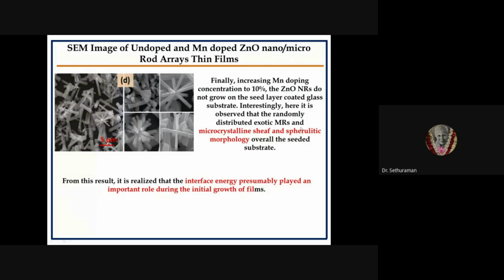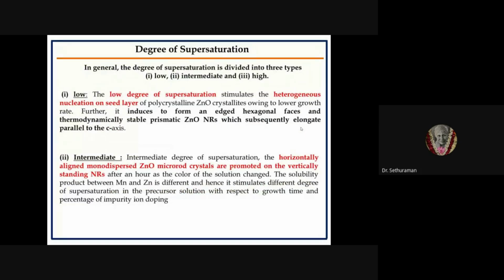Here, zinc oxide nanorods are not growing on this seeded substrate. So it is completely a microrod assembly on the surface of the glass substrate, with distributed microrod assemblies of different structures like a sheaf as well as spherulitic morphology, overall on the seeded substrate. From this result, we realized that interfacial energy presumably played an important role during the initial growth of films. So in general, we compared the degree of supersaturation with three different types.